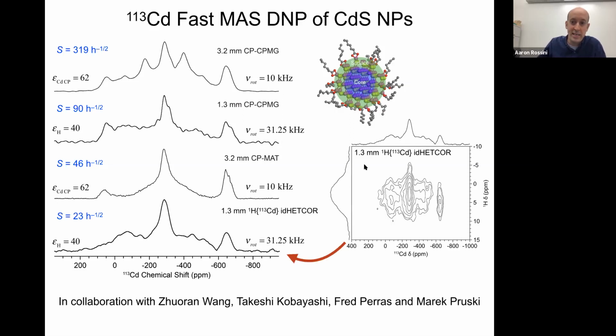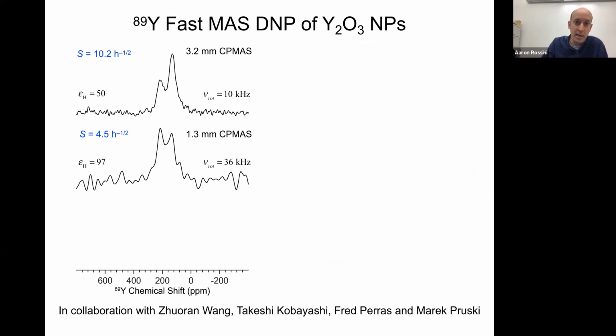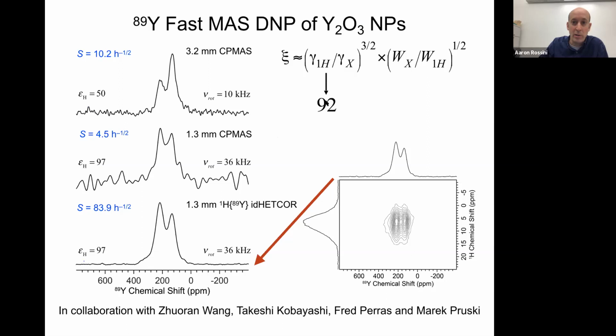Now, if we try and do the proton-detected cadmium experiment with the ID HETCOR type approach, we actually lose sensitivity. The reason for that is CPMG is very efficient in this system. We have a very long T2 prime. The other thing that holds back the indirect detection here is the fact that the CP is relatively inefficient. Your nearest proton is a couple angstroms away from the cadmium, so that leads to really low CP efficiency and prevents the proton-detected experiment from providing a net gain in the sensitivity. I'll just go through this quickly and say, if we go to a nucleus with a much lower gyromagnetic ratio, yttrium-89, these are yttrium-89 DNP SENS experiments on yttrium oxide nanoparticles.